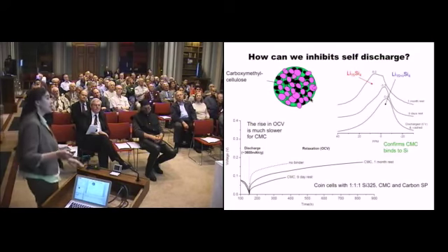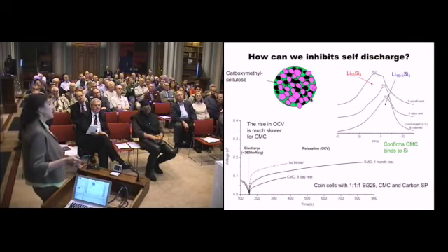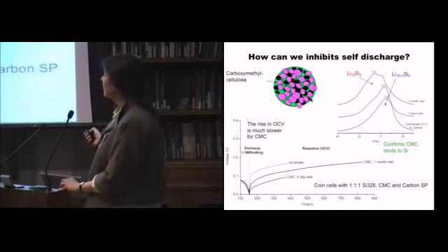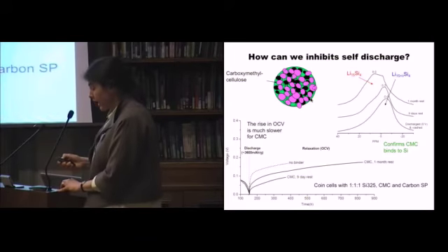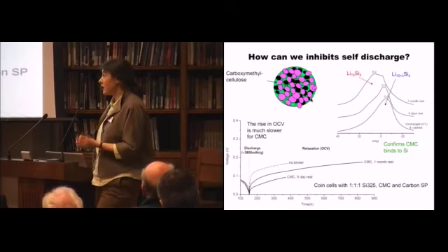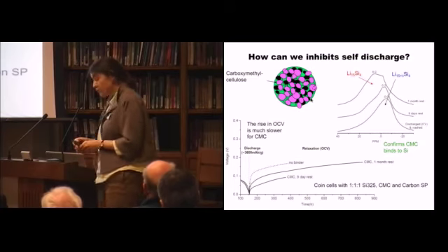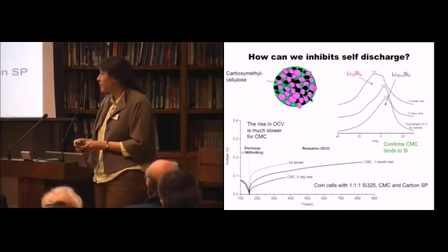And it turns out you can take a binder, such as a cellulose material, and that cellulose material covers the silicon, and you can reduce this decomposition reaction so that instead of happening in minutes, it now takes about a month for it to happen. And it's solving these types of discharge mechanisms that's important if a material is ever going to be commercial.